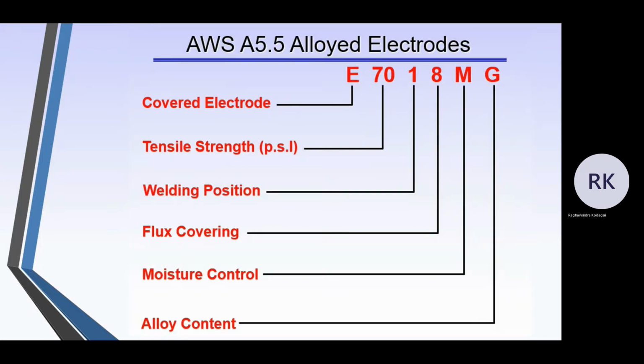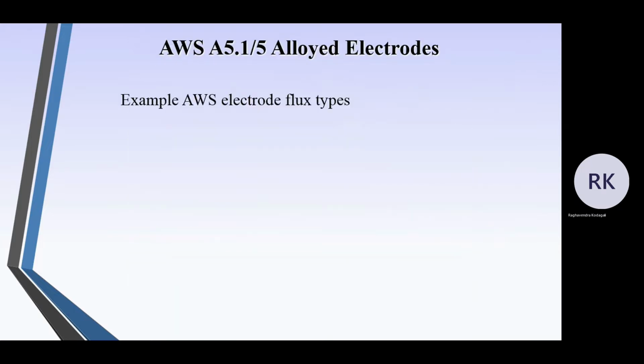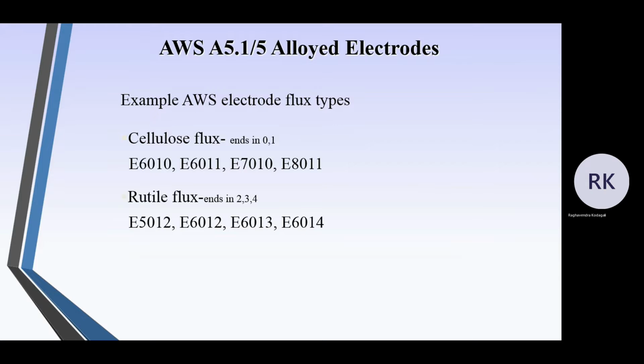So this is AWS A5.5 alloyed electrodes. So you can know normally when we are talking 70-16, 70-18. So you know the M is for moisture control and G is the alloying element. So cellulosic flux ends in 0 and 1. That's why it is 0 or 1 in this case of electrodes 7010, 6010, 6011, 7010 and 8011. And rutile, it ends with 2, 3 and 4. So 5012, 6012, 6013, 6014, these are all rutile fluxes.